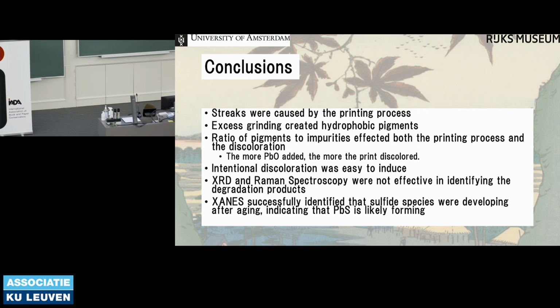XRD and Raman spectroscopy were not effective in identifying the degradation products, but XANES was, showing that a sulfide species was developing after aging, at least in my reconstructed samples, indicating that lead sulfide is likely the form of the discoloration.